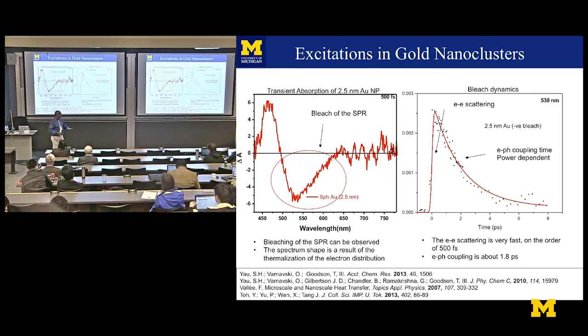Some people always talk about a chain-link fence, right? I kick the chain-link fence, and then sometime later, you feel what happens on the chain-link fence down at the end of the fence, right? Okay, and this is what this is doing. It's like you apply an impulse to the fence. And so this electron-phonon coupling is about 1.8 picoseconds, and the scattering of electrons is about 500 femtoseconds. This is typical. People had seen these kinds of things in big particles before.